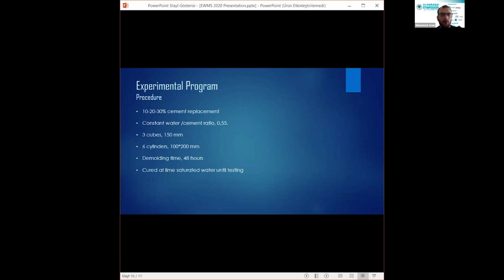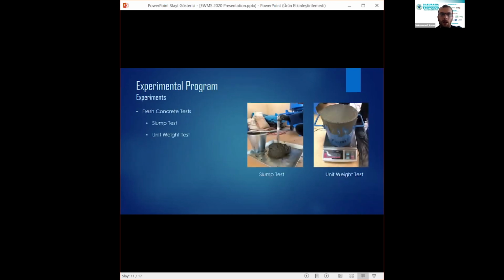Demolding was performed after 48 hours, and then the specimens were subjected to moist curing in lime saturated water at 22 degrees centigrade until testing. We implemented a slump test of fresh concrete to evaluate the workability of concrete, and a unit weight test.